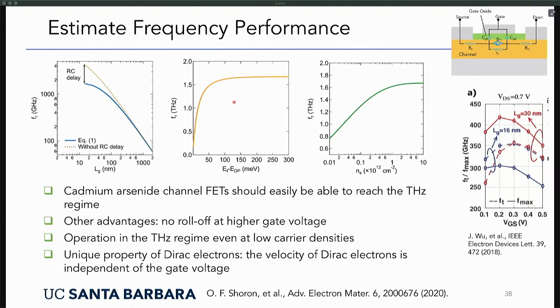Okay, so that's very high. And there's other attractive properties. For example, there's normal semiconductors, which has something to do with the parabolic bands of normal semiconductors. There's a drop off at high carrier densities in that cutoff frequency. That will not happen for cadmium arsenide, and this is something to do with the Dirac electron properties. Okay, and you can also maintain these relatively high cutoff frequencies to fairly low charge carrier densities. That's, for example, important if you're concerned about heating effects and so forth.